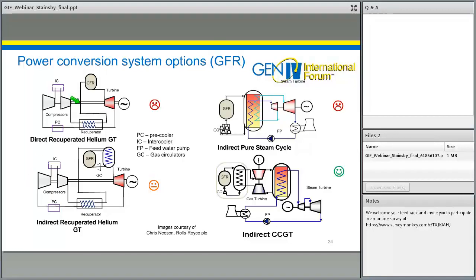in top left, a direct recuperated helium gas turbine. So the reactor coolant drives the turbine. We've got a recuperator, recover waste heat, two-stage compression, intercoolers and pre-coolers and things like that. Through all the other permutations down to the one which we eventually adopted as a reference, which is actually the indirect combined cycle gas turbine, where we use the heat from GFR to heat a heat exchanger.